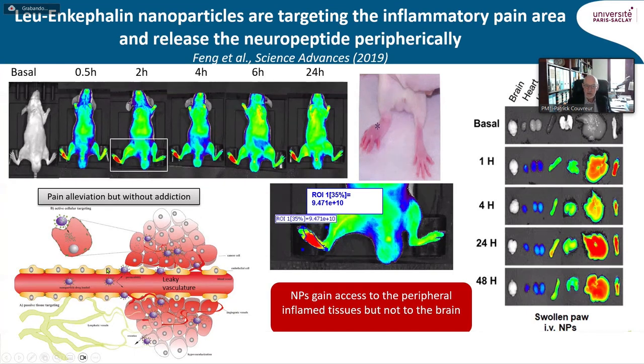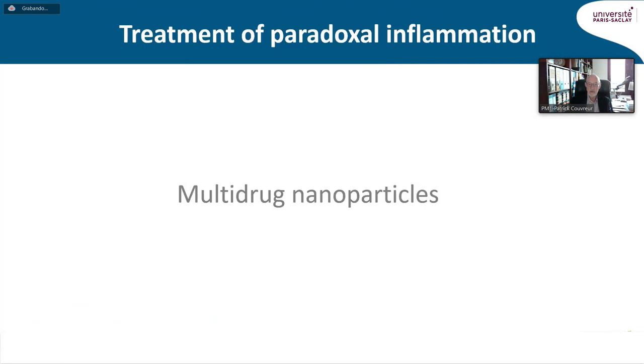And in fact, this is explainable by the fact that at the level, as you can see here, of the inflammatory painful tissue, you have a leaky vasculature, which allows those leu-enkephalin squalene nanoparticles to extravasate in a highly specific manner at the level of the inflammatory tissue and to release the intact neuropeptide at this level. Whereas, as you can see here, those nanoparticles were unable to pass the blood-brain barrier and to enter into the brain tissue. And it is for this reason that those nanoparticles allowed pain alleviation, but without addiction, as is observed with morphine or other opioid derivatives.